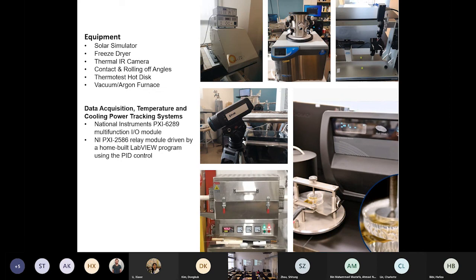So for the cooling paper, I mentioned that to you. The original cooling paper, the cellulose fibers, is hydrophilic. The contact angle actually is around 85. And with the PTFE coating, we are able to change the surface from hydrophilic up to super hydrophobic, not only hydrophobic, because the contact angle turns out to be 165 degrees. And also we ran the outdoor test. We just set up our cooling paper at the roof of our engineering building for 1 month, 30 days, and brought it back. It still maintains pretty nice mechanical properties, including the contact angle up to 165 degrees.